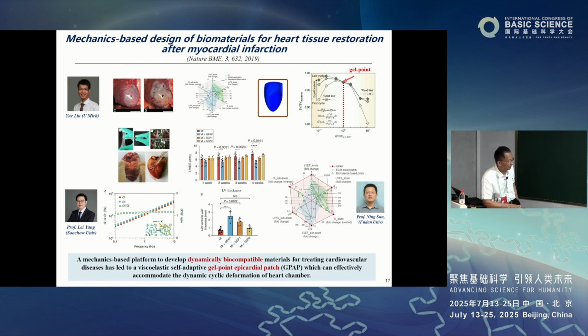Then we tested it in the rat, and we showed the so-called GPAP, the gel point adhesive patch. This blue material outperforms all the others. So this is untreated. This measures the ventricle thickness, the heart chamber thickness, after 4 weeks. If the heart is untreated after a heart attack, the chamber becomes very thin. And these are comparison materials. This specially designed material outperforms everything else and becomes the best. This is the comparison chart for all the existing therapies, all existing materials. So our mechanics-based design outperforms all the other materials. So this means you can use mechanics to help design material properties that can best help our tissue restoration and also health recovery.